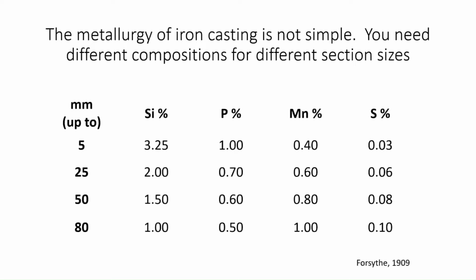These two irons were so different, you can't really imagine that they were anything like the same sort of material. But you could take a specific composition of iron and cool it quickly and you would get white iron, and cool it slowly and you would get grey iron. So speed of cooling was an important part of the reason why you would get these two metals. But the other thing was chemical. If you wanted to get grey iron, and everybody who wanted to make a casting wanted really grey iron, then you had to have a high silicon and phosphorus content, because that encouraged precipitation of graphite. So that was the first phenomenon.